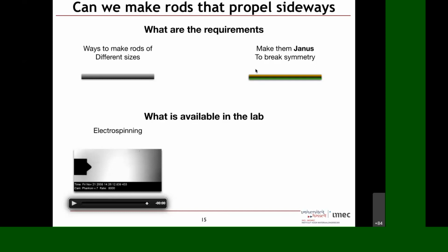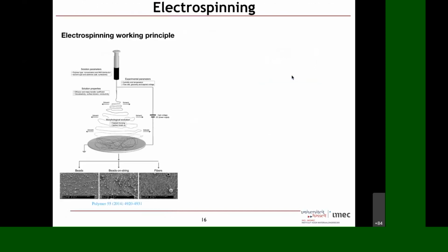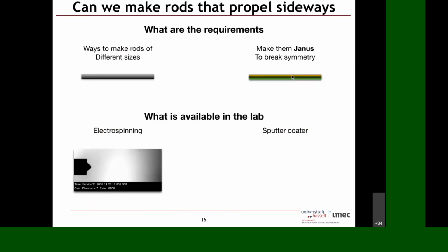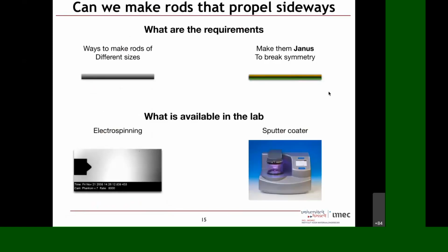How can we break the symmetry? I was using something called a scanning electron microscope. And to do a good scanning electron microscopy, you have to coat the material with some kind of a metal layer so that when the electron hits the material, some of them come out, and the ones that are going into the material have to go somewhere, or else it'll kind of charge. So electrostatics, static will build up, and then you're not going to get a good image. So you need to put a small metal layer so that the electrons can conduct to the metal layer and go into the ground.